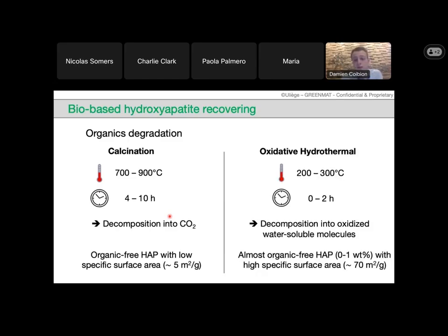The other technique is one that we are developing at the moment in our lab, which is called oxidative hydrothermal treatment. So we are able to degrade the organic matter into oxidized water-soluble molecules, and we are doing it at a lower temperature compared to calcination, between 200 and 300 degrees C.